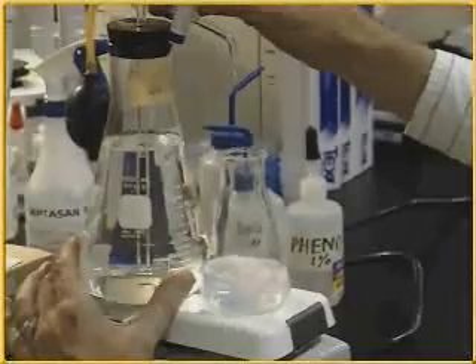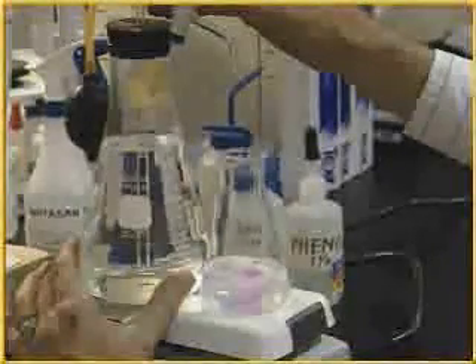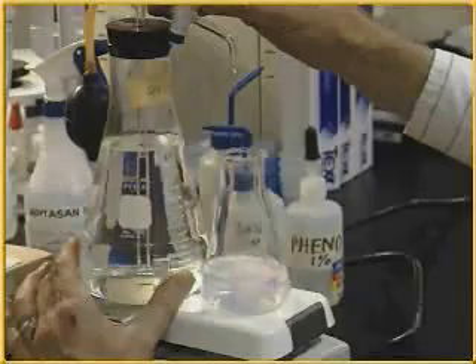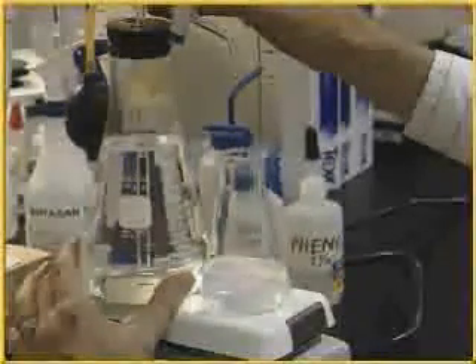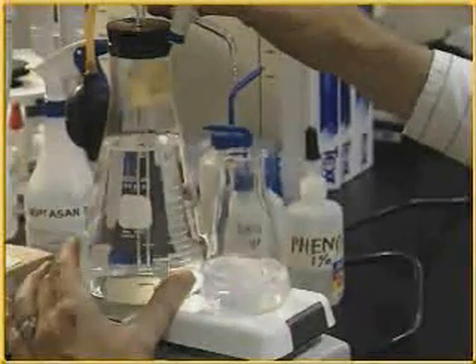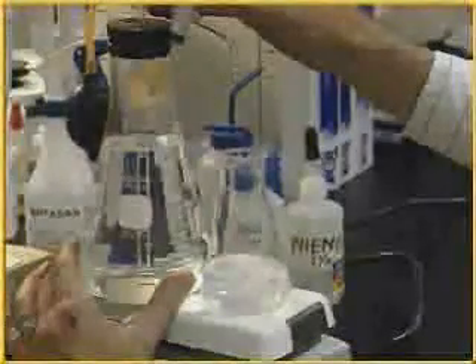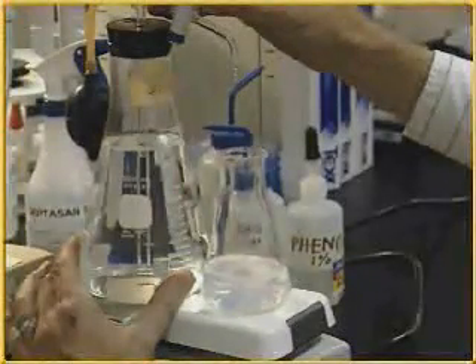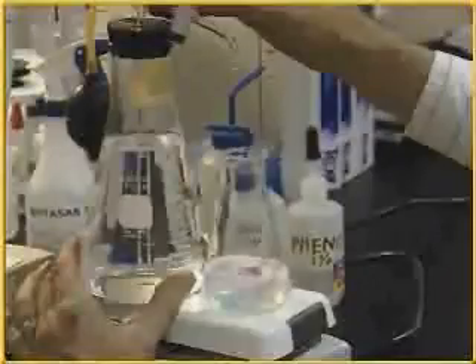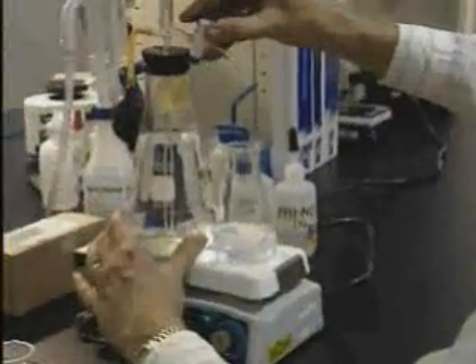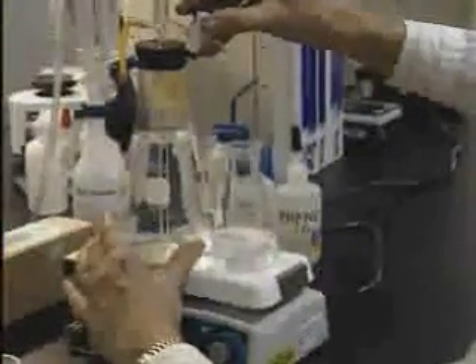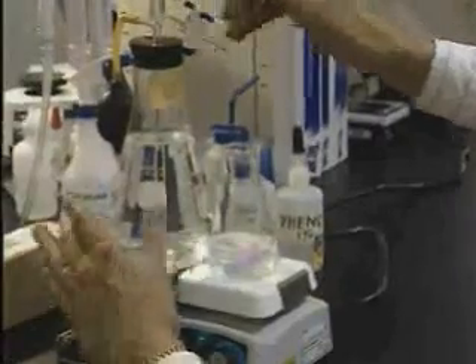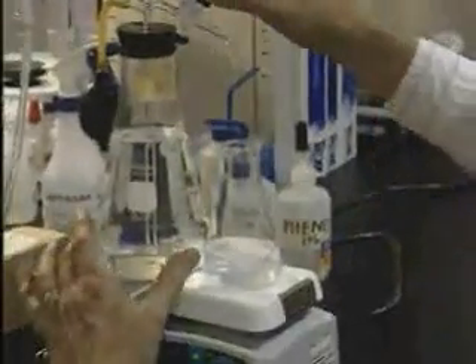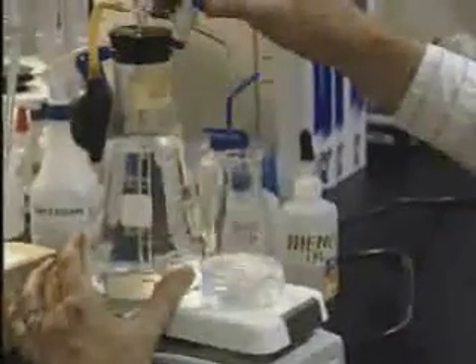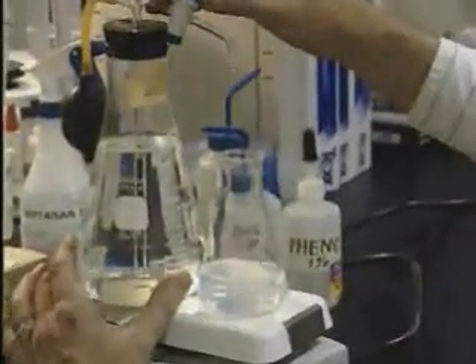Fluctuations in bath concentration can cause changes in the coating. Concentration must be closely monitored. Fluctuations in concentration can cause flash rusting, streaky coatings, over or under phosphatized parts, and pitting. The best method of monitoring bath concentration and acid consumed levels in the field is titration. The burette method is the most precise and therefore recommended. Glassware should be cleaned and rinsed with DI water before titrations are performed.